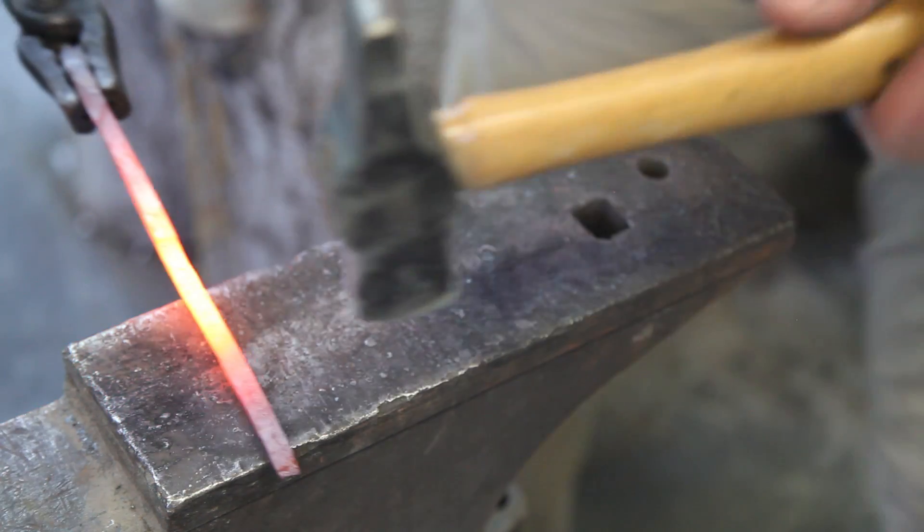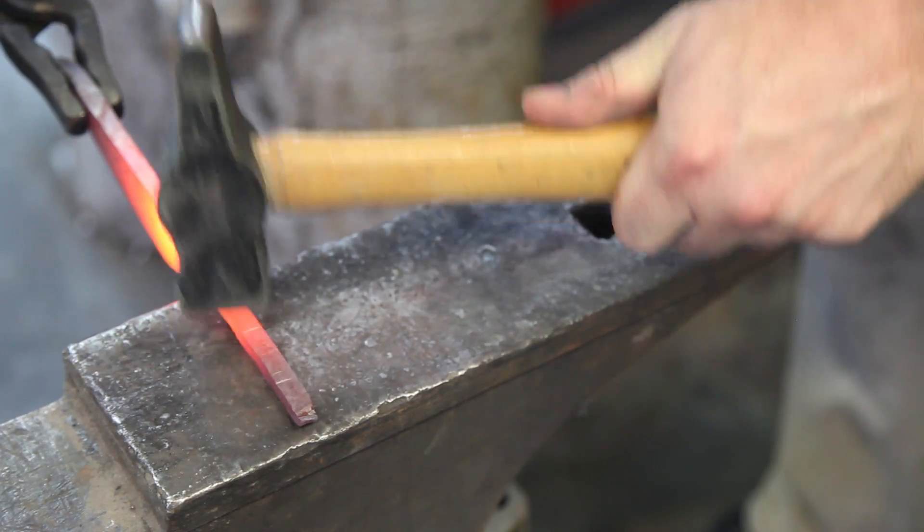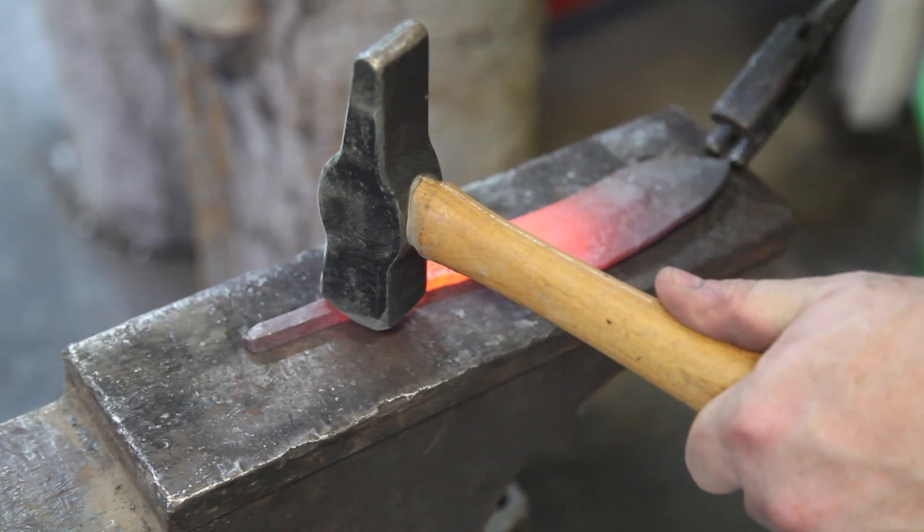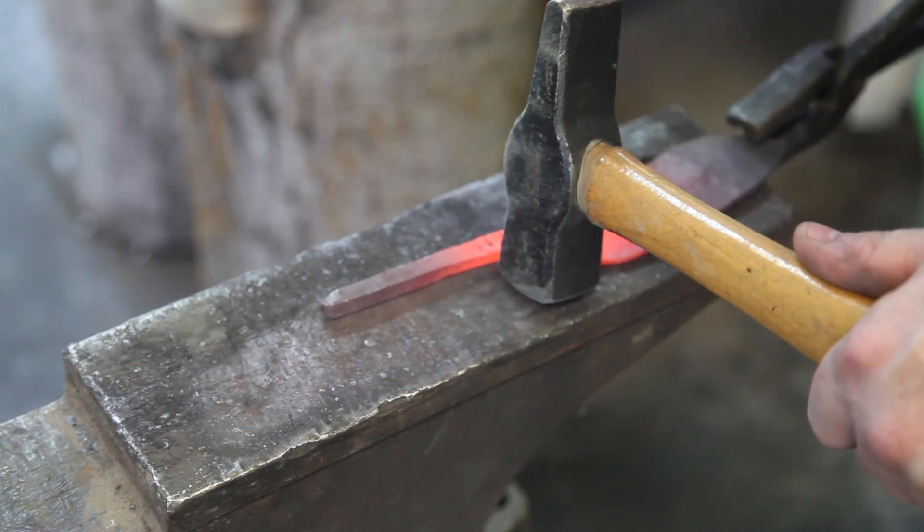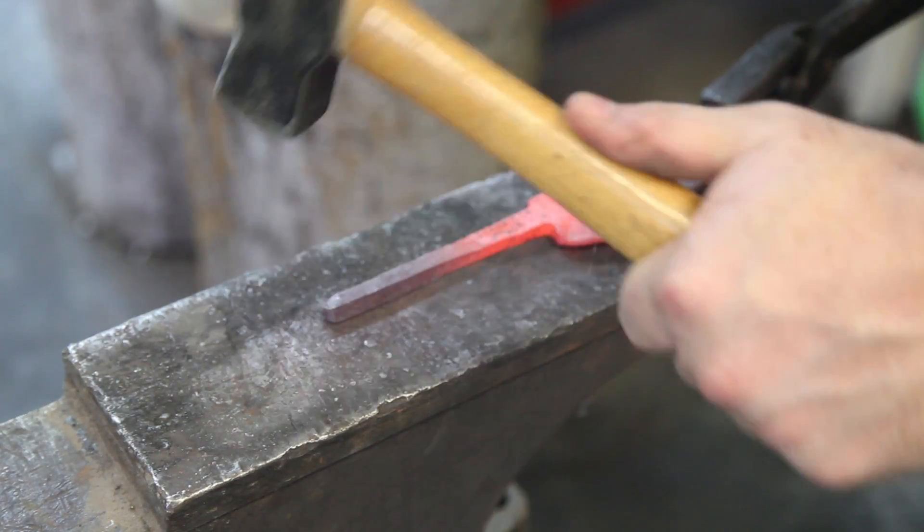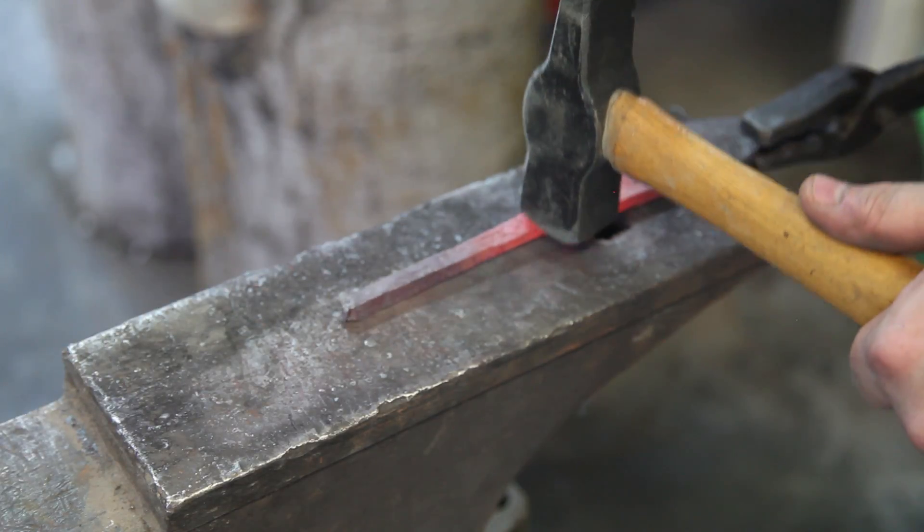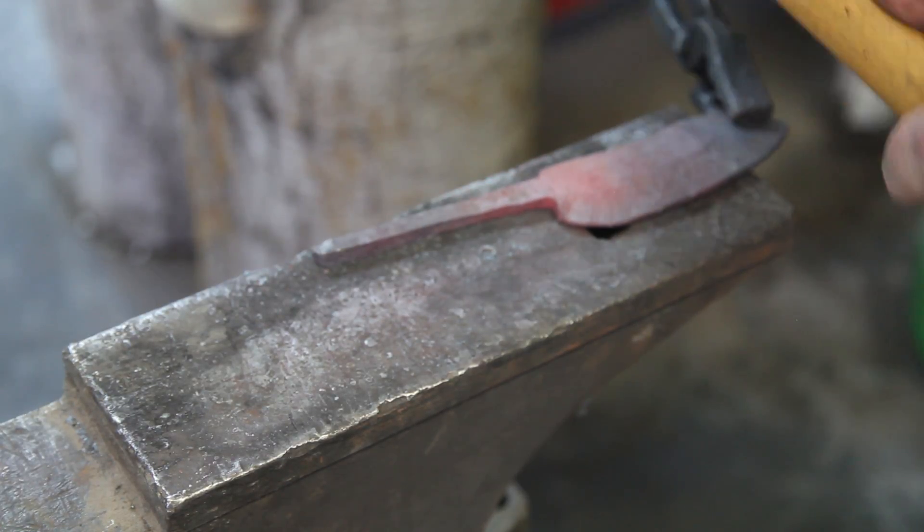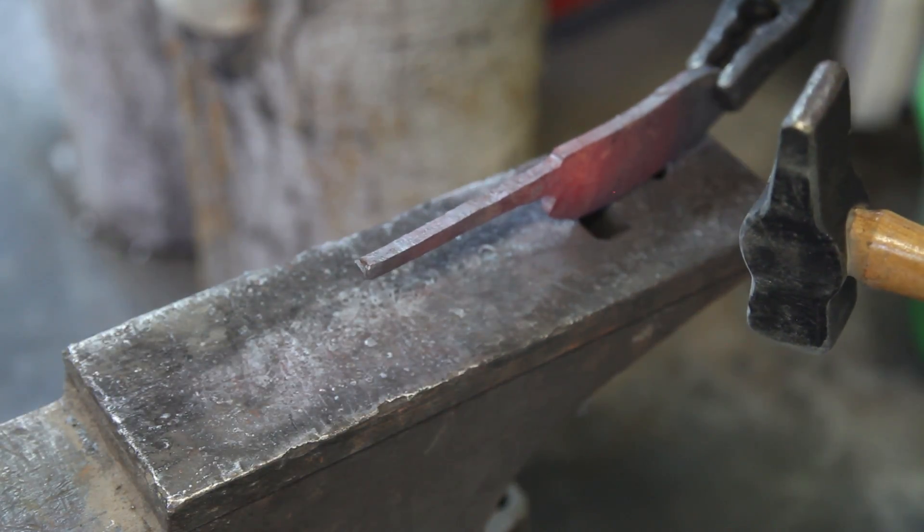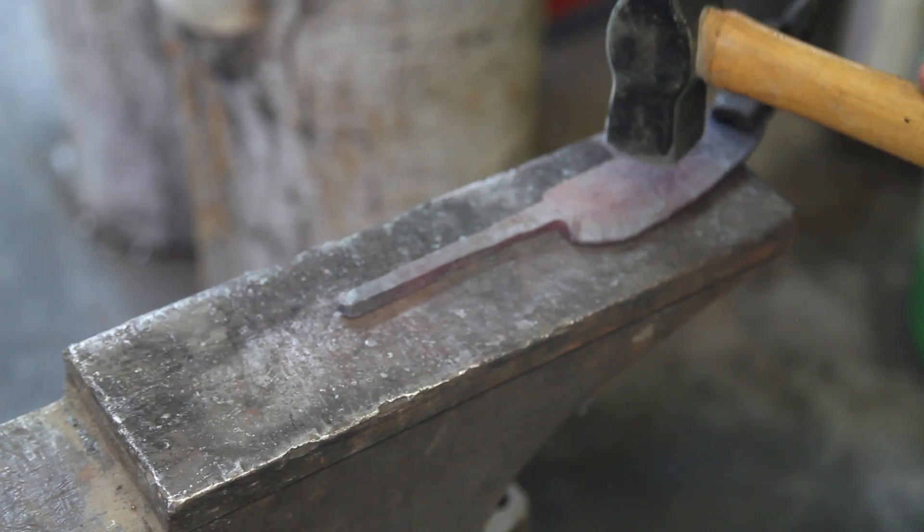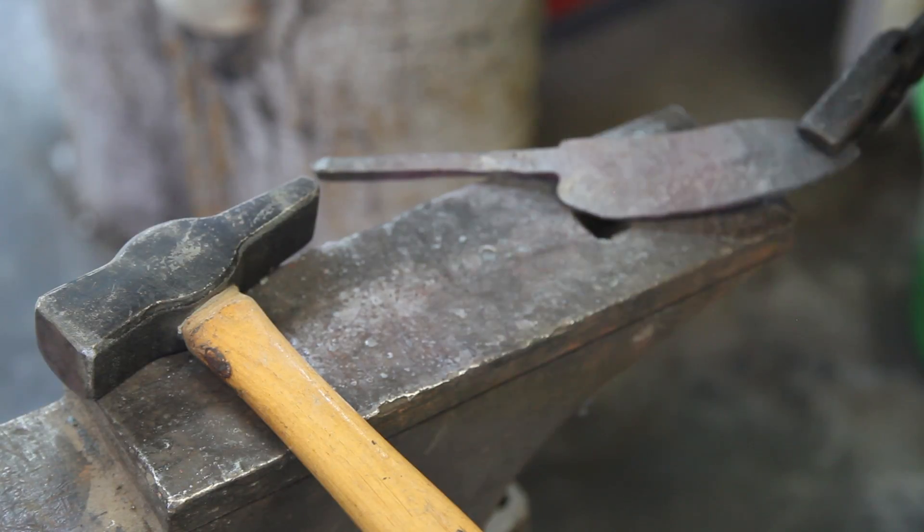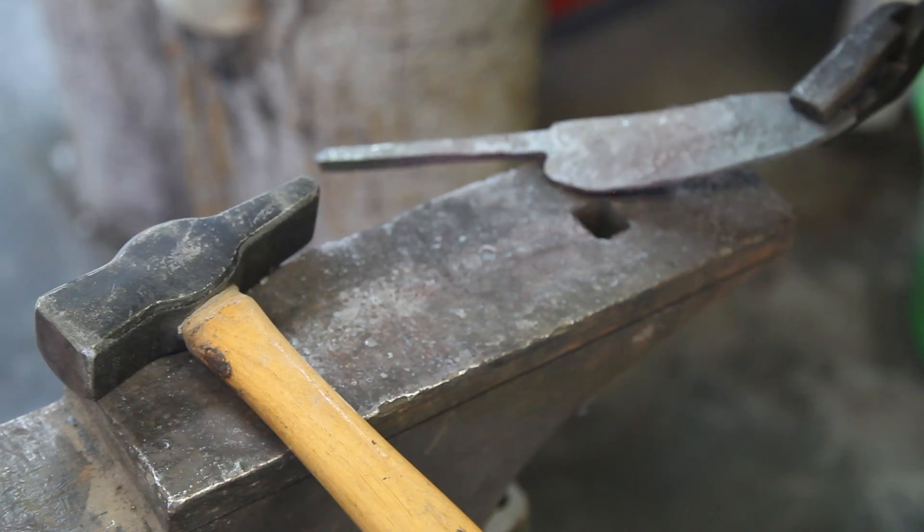What I'm going to try to do now is just one last little kind of go over it and try to make sure that everything's basically straight, or at least as straight as I can make it, and flat, because the next thing I'm going to do is I'm going to anneal this. Which, as I talked about earlier, means heat it up in the oven to a critical temperature. In this case, I'm going to say 1500 degrees, since that's the temperature I was able to get it to harden at earlier. And then I'm going to cool it down very slowly back to room temperature, and the purpose behind that is to relieve all this stress that I've introduced in that. You can see how much the blade turned, and I'm going to have to correct some of that by grinding.